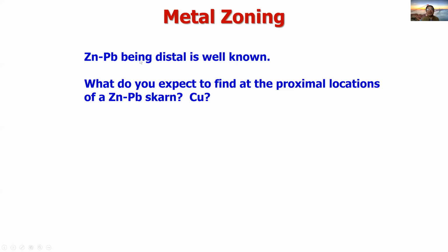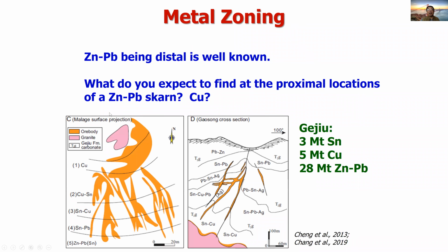Zinc lead being distal is well known, but a lot of the time people are thinking, oh, I have zinc lead, I trace it back to the intrusion, I should have a copper. Watch out for this. You may not have a copper, you may get a zinc, you may get a tin skarn. So watch out for this. And that's the example in China, Gejiu deposit. 3 million tons of tin. It's a huge, giant deposit. And you go out to zinc lead.